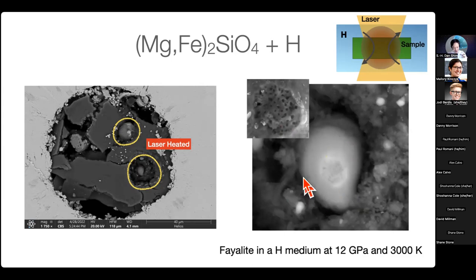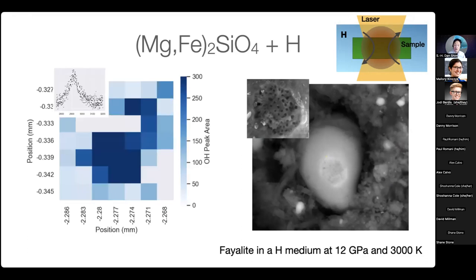And they actually integrated and collected together in a liquid state and formed this type of sphere because of the surface tension. And the surrounding area that you can see, sort of loose powder, is leftover oxide after losing silicon to the metal. For this sample, we are able to conduct the 2D scanning of Raman scattering, which allows us to measure the OH vibration of the water. This blue area is the area where we detected the strong OH vibration signal, which is mainly from the surrounding area. So we have a direct evidence of formation of water.